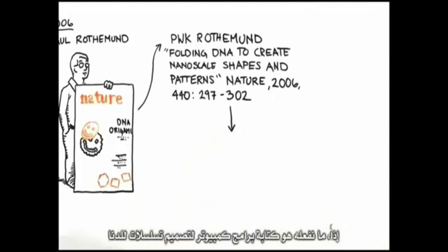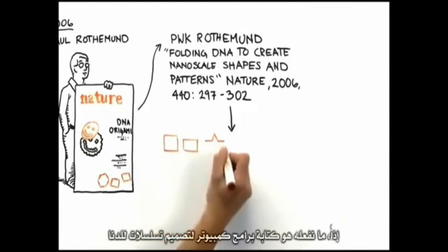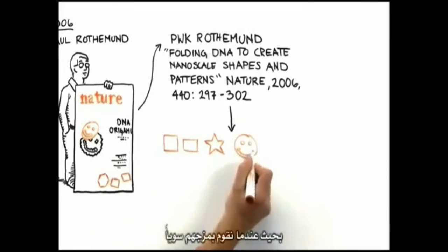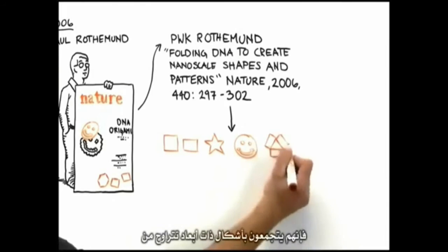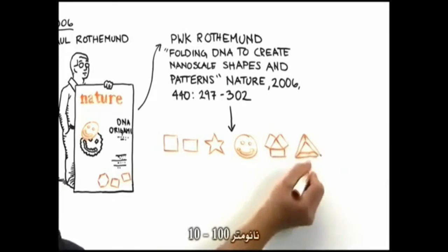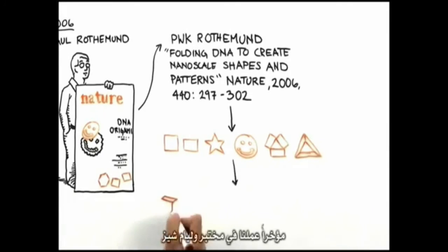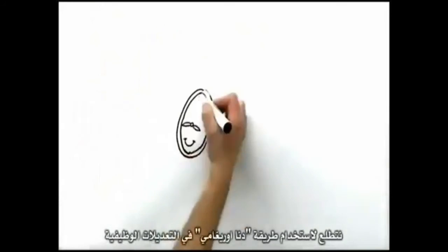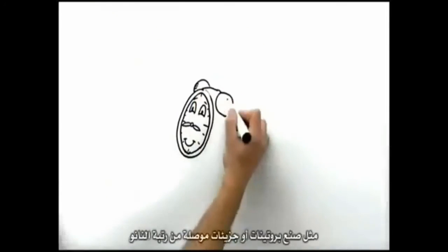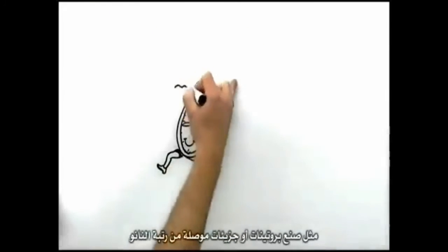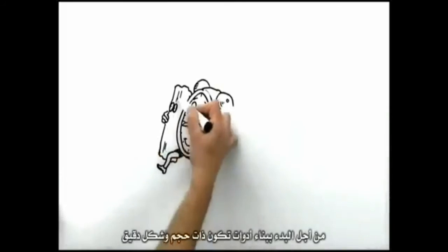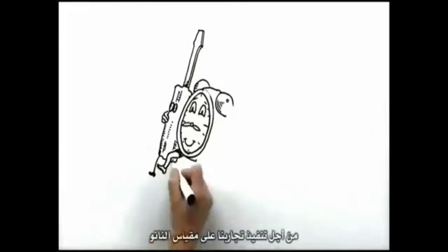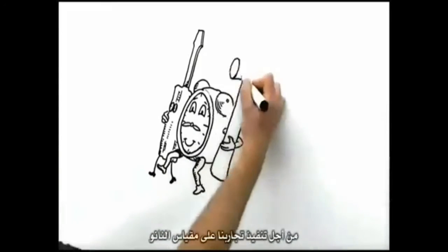So what we do is write computer programs to design sequences of DNA such that when we mix them together, they self-assemble into desired shapes with dimensions of 10 to 100 nanometers. Recently, we worked in William Shih's lab to extend the DNA origami method to create 3-dimensional shapes. Looking forward, we're currently using DNA origami along with functional modifications such as protein or nanoparticle attachments in order to start building tools that are precisely the right size and shape for carrying out experiments on the nanoscale.